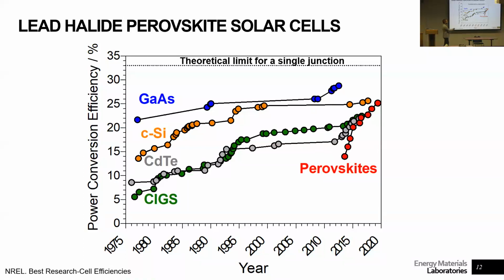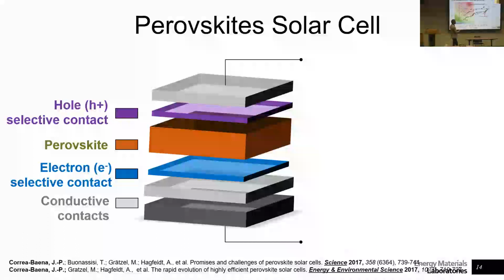And you can see what happened here with perovskites. In just 10 years or so, researchers like me in the lab were able to get to now 26%. We're right around the same efficiency as a crystalline silicon solar cell, 26.5, I think, percent is the crystalline silicon, whereas perovskites are at 26.1. So really, really fascinating growth in efficiencies.